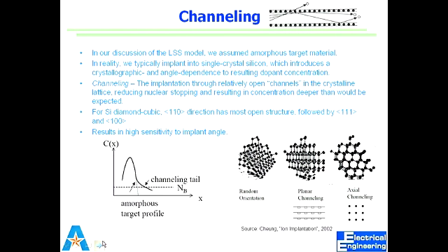In a lattice unit cell, you have 4 atoms on the top level, 4 atoms at the lower level, and this building continues on. If I'm standing in the center and look up, I don't see any atom. I can zap through that. This is what gives rise to the idea called channeling.